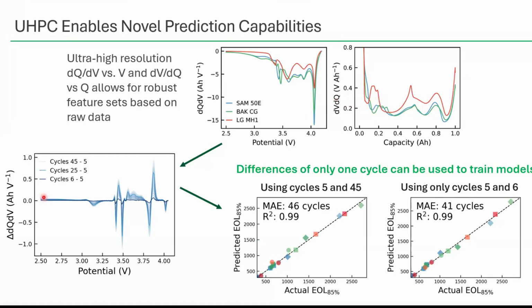There's a representative chart here of a plot that shows the differences as we cycle a cell, the residuals of each cycle of DQDV. You can see between cycles, say 5 and 6, the darkest line, there's some very tiny differences in the DQDV, which you can pick up very cleanly with UHPC data. These just amplify over time into some very big differences, meaning these DQDV peaks are shifting and moving.